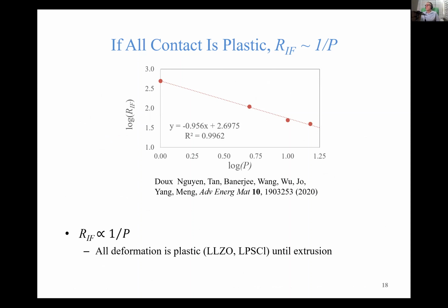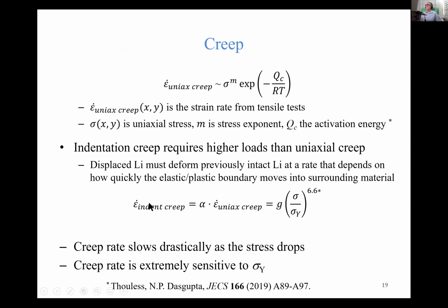Here's some data from Shirley Meng's lab looking at LPS chloride. Up to 15 megapascals, I again took her data and we plotted it on a log-log plot. We get a very nice straight line with a slope again of -1. So in this case, again, all deformation is plastic, for both very hard and less hard solid electrolytes.